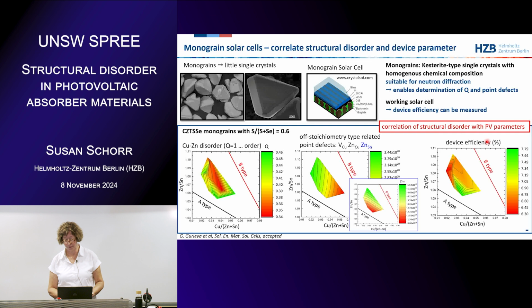And this is the device efficiency. Of course, it's not great. It's 7.8%, so it's a normal batch for them. They have the record of 12 point something, I think, for the pure sulfide monograin solar cells. But you see that you get the highest efficiencies here in this corner, where you have the lowest copper zinc disorder and the lowest concentration of the zinc on tin point defect. So in this study, we could correlate very nicely the structural disorder with PV parameters.